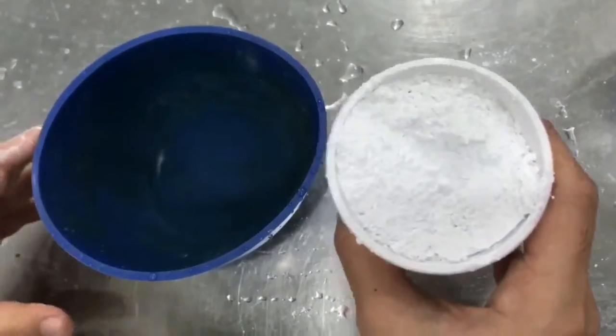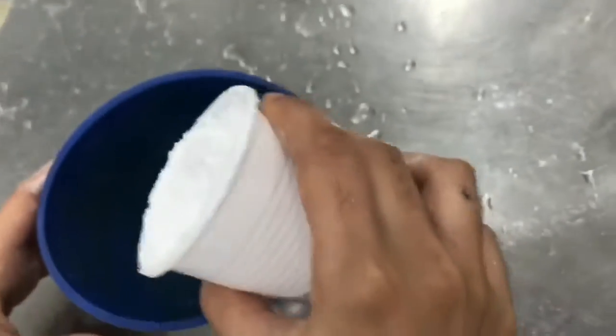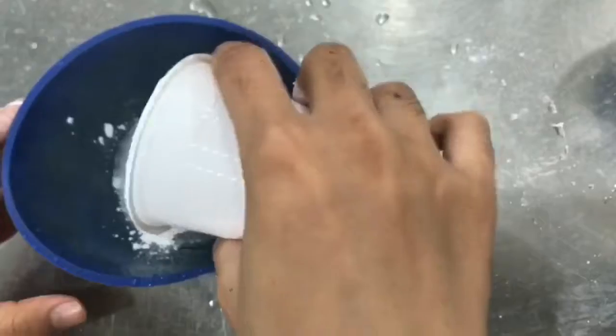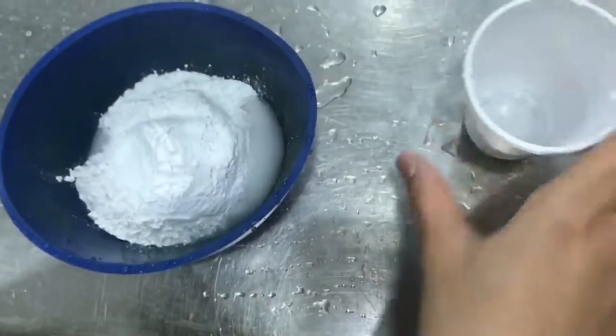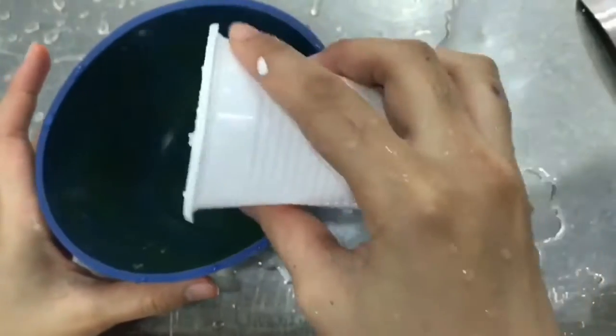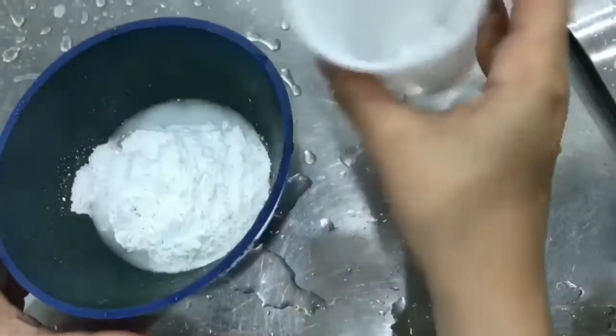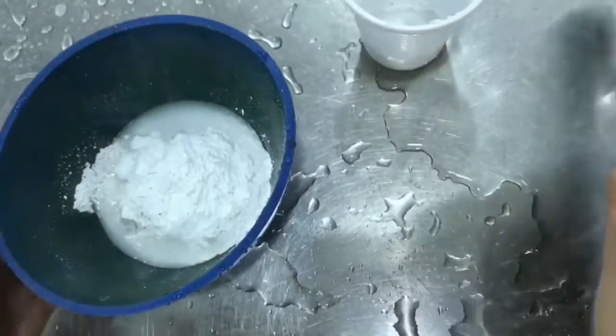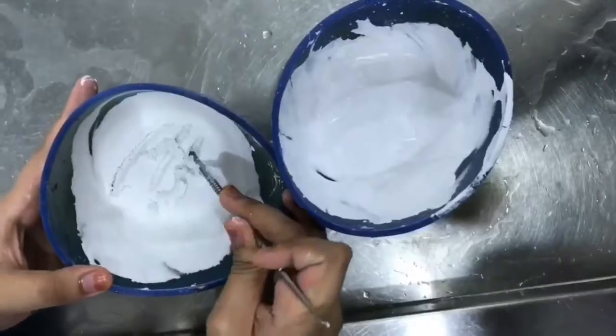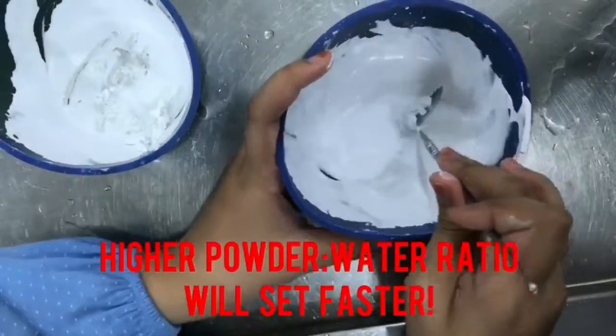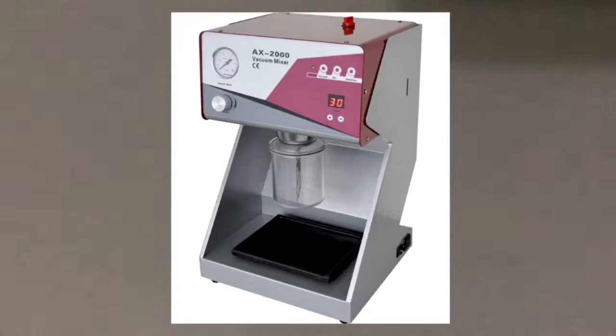Now we're going to see the effect of powder-water ratio on the setting time. First, we're going to use 1 cup of powder, POP, and half cup of water. We use the same technique of mixing the powder and the water. Next, we're going to use half cup of water and half cup of powder. And again, we use the same technique of mixing. The first mixture, which has a high powder-water ratio, set faster than the other. A vacuum mixer can also be used as it sucks the air, thus helping to eliminate the air bubbles.